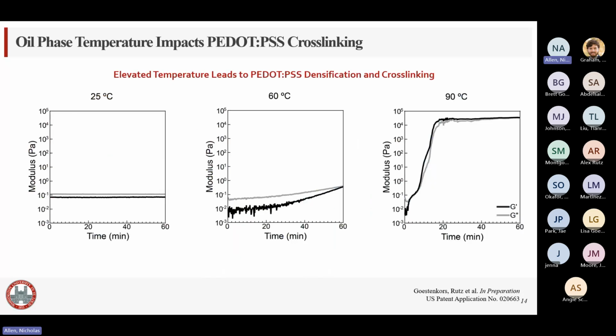There have been studies in the field on what exact temperature does to the aqueous colloidal dispersion, and research has found that temperatures between 60 degrees and 90 degrees Celsius induce behavior in that aqueous colloidal dispersion indicative of cross-linking. So for my study, I decided to conduct emulsions at 25 C room temperature as a control, as well as the ends of those spectrums, 60 degrees Celsius and 90 degrees Celsius. And in the field, we can use what's called oscillatory rheology to evaluate the cross-linking of polymer solutions. So what you're seeing here is the PEDOT:PSS aqueous colloidal dispersion under 3 different temperatures.